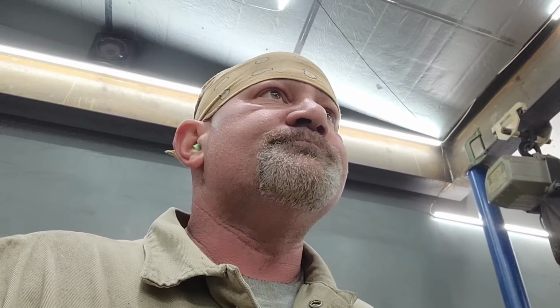So I can dance around that fast with the 5/32 5P plus and then go back with either a 3/32 or a 1/8 inch 7018. And with that rod, once I've got a pass of 5P in there, when I go in with my 7018, I'll really be welding and I'll really be trying to fill it with material then. With the 5P, I don't want to fill it with material. I just want to burn the trash out of there, make a good seal on it, and create a surface to weld on. So now we're going to go into that part of it.